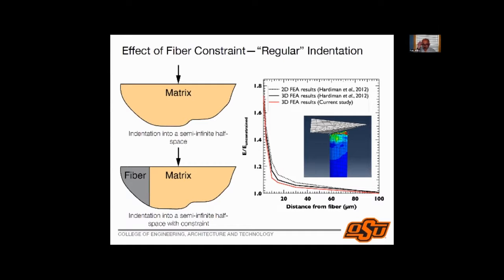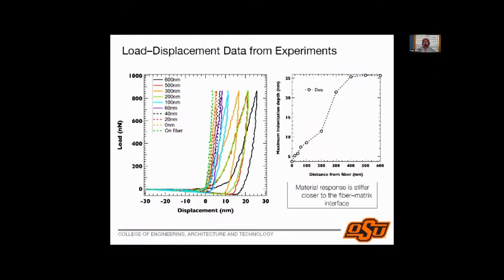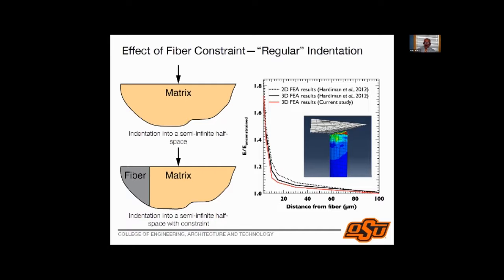So from an elasticity viewpoint, the question is, as I get closer to the interface, is this getting stiffer because I am seeing a different material property, or is it getting stiffer because I am seeing constraint because of the fiber? And this has never been addressed until the work we did, because there are no analytical solutions to this. So there are some finite element solutions.